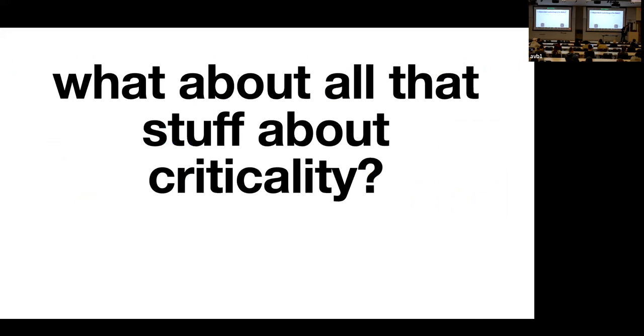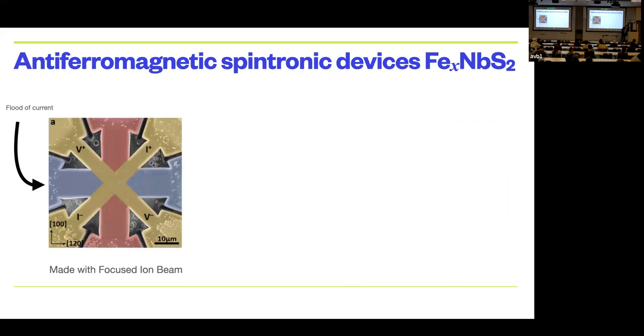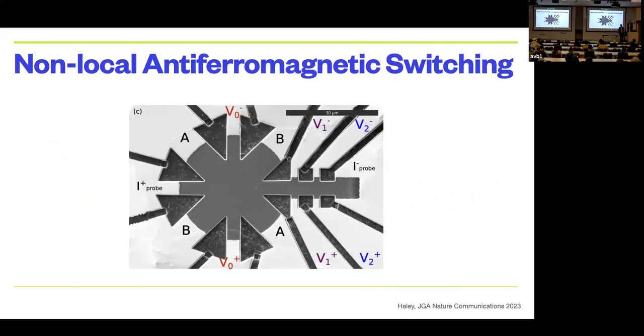When we have this device, it's actually stuck on a substrate with some epoxy, right? Which means that its length is fixed. If its length is fixed, imagine I'm pulsing current in this direction, and I mentioned that the structure must be anisotropic. So if I'm pulsing current in this direction and I'm turning this into a single domain, it means that I'm either stretching or shrinking this part right here, depending on which way the domain goes. Because before it was all domains, now it's just one domain, which means I'm stretching it in one direction. Does that make sense?